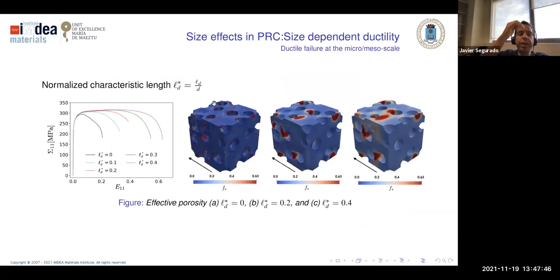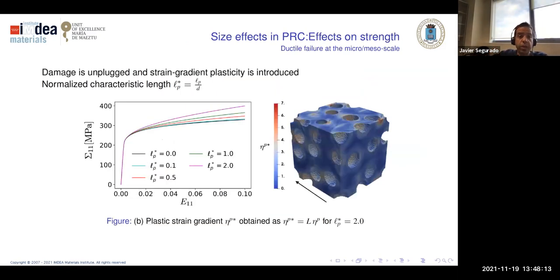What else can we do? We can check the effect of the particle size on the ductility, and what we see is that the smaller the particle, smaller meaning D tending to 0, the more ductile. This is not true if we consider particle fracture, but it's true if we just consider matrix softening. That happens, for example, at high temperature. The other thing that we can do with this model is to predict the size effect on the strength. So what is the difference in the strength of the material depending on the size of the particles?